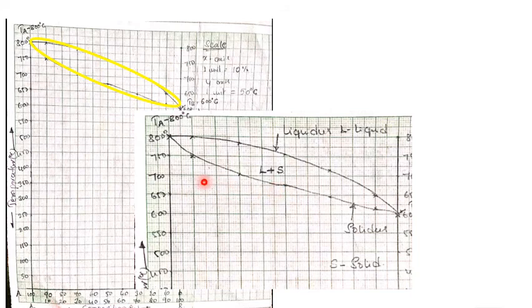So easily we can say now, for example, if I take some 700-degree temperature and this alloy composition, at the intersection of these two lines, I can say the number of phases present is 2. The number of components is 2. Pressure is maintained constant, so temperature is the only variable. So easily we can say P plus F equals C plus 1. So 3 minus 2, that's only 1. So 1 is the degrees of freedom.